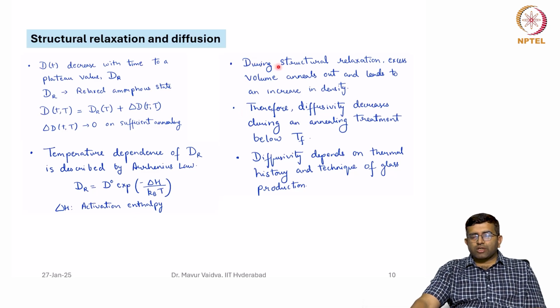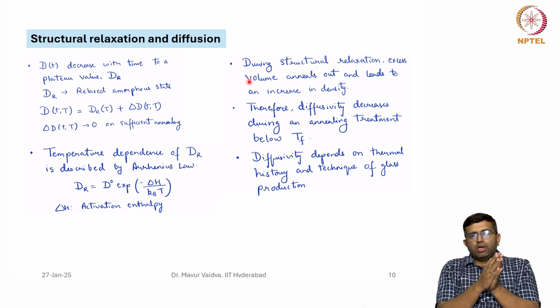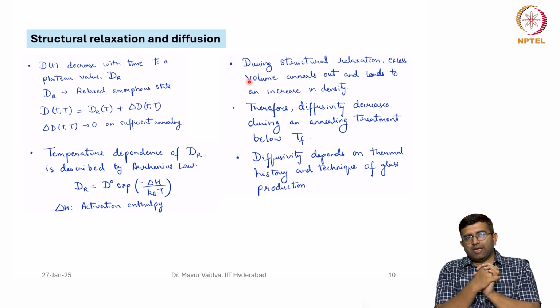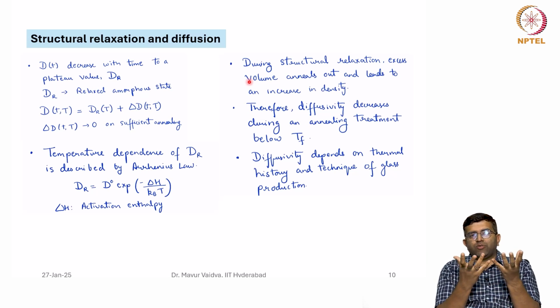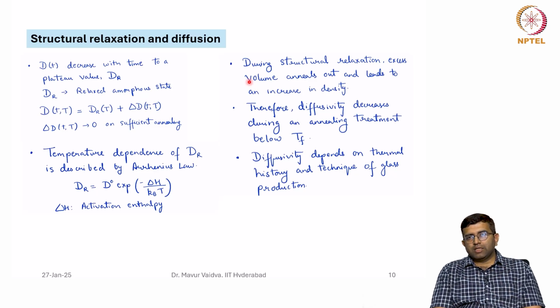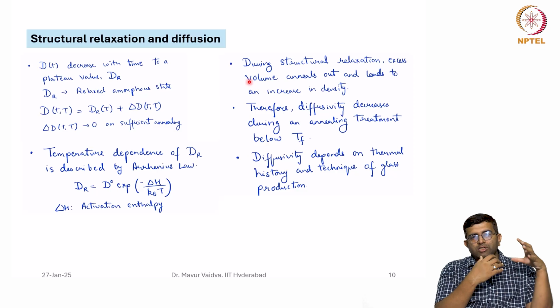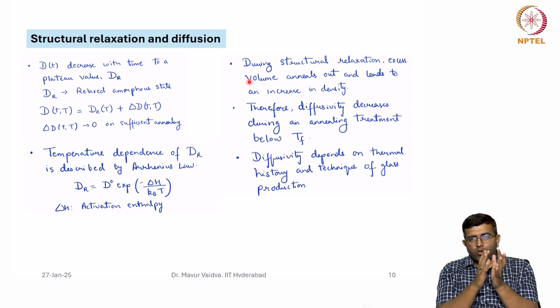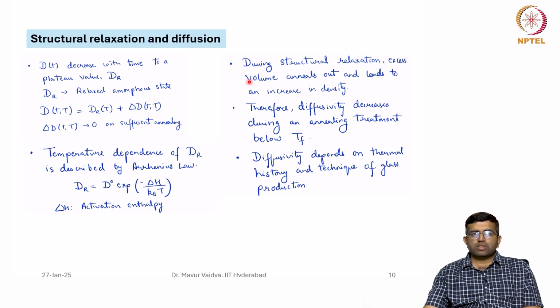Now, during structural relaxation, excess volume anneals out and it leads to an increase in density. The excess volume, that is the free volume that is present, anneals out and it leads to an increase in the density of the glass. And therefore, the diffusivity decreases on annealing treatment below Tf, because earlier you had a more open structure, and now with the increase in density it becomes more packed, and hence during structural relaxation the diffusivities tend to decrease. So the diffusivity depends upon the thermal history and the technique of glass production.